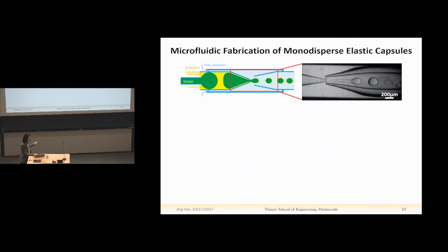And this video shows a real generation process. As you notice, when the water slugs break into small drops, we get the double emulsion. But in between two slugs, we have the oil phase only, and this oil will become single emulsion droplets like this. Because these oil drops have very different density from the double emulsion drops, later on, after we collect them, we can easily separate them by gravity. And also because the solvent that we use in the middle phase oil has substantial solubility in water, it will diffuse into the water phase. So only the polymer is left over to form a thin shell of the capsule.